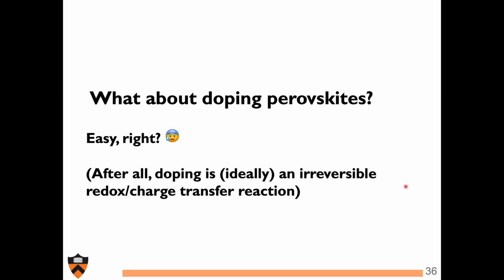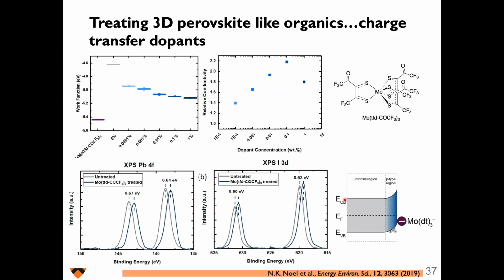And this is one nagging issue, this irreversibility, because perovskites do feature ion migration. A lot of ions will just come in, and if you want to affect change, say dope it, something else will come in and stymie that potential reaction. And this has a lot to do with our lack of substantial success with doping perovskites in general. The way we started down this path was with using molecular oxidants.